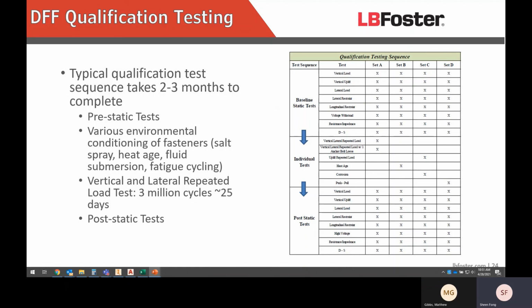From there, we'll do a conditioning of the fasteners, typically a salt spray or a heat age or fatigue cycling, which is the vertical and lateral repeated load test. This test is typically 3 million cycles and takes about 25 days to complete. And then from there, we'll do the post-static tests, which is basically a repeat of the pre-static test to verify that the fastener performance has not degraded.